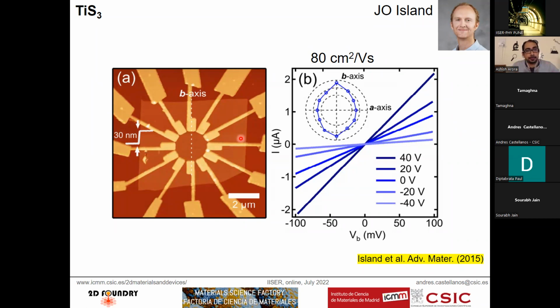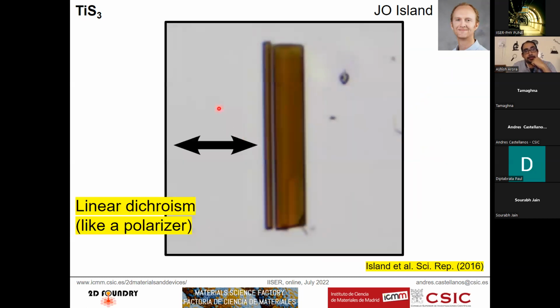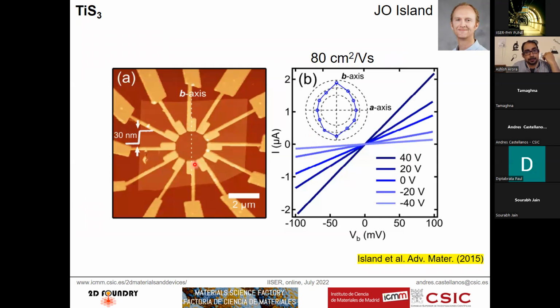I see. That's quite good. And have you done polarization-resolved absorption measurements on this? Because I was curious, what's the shift of the band edge in terms of energy or wavelength when you go from one polarization to the other? I don't remember if we have done that, because I think we installed our micro transmittance setup later. I think we studied just the transmittance with the red, green, and blue channels from the pixel cameras, and we fabricated photodetectors and used polarized light.